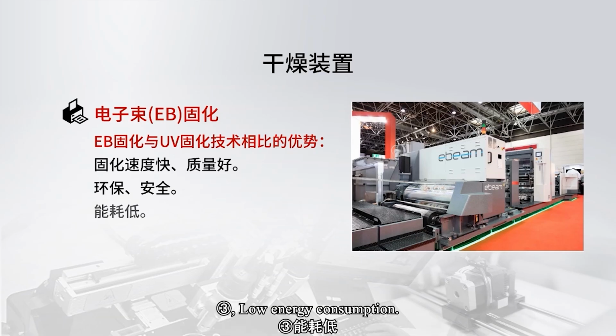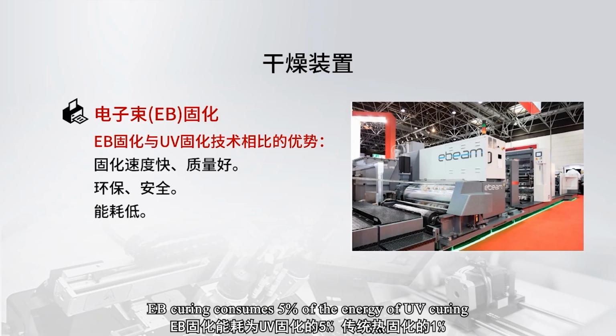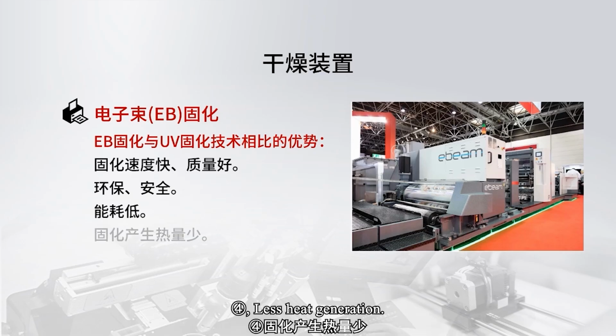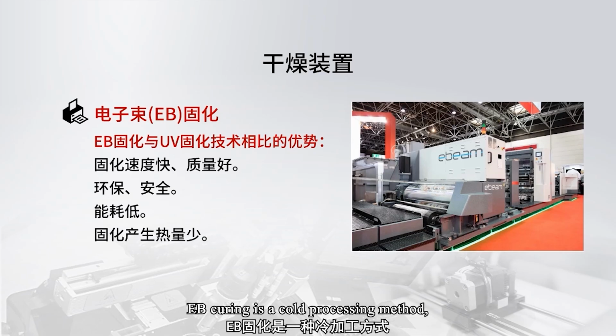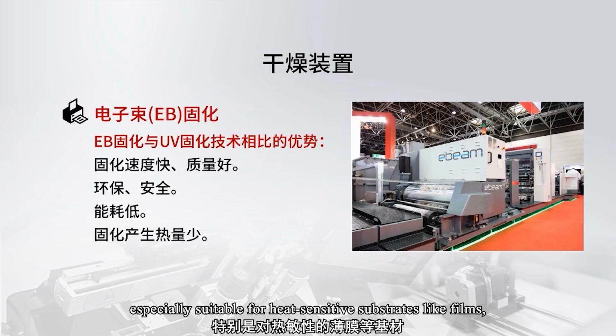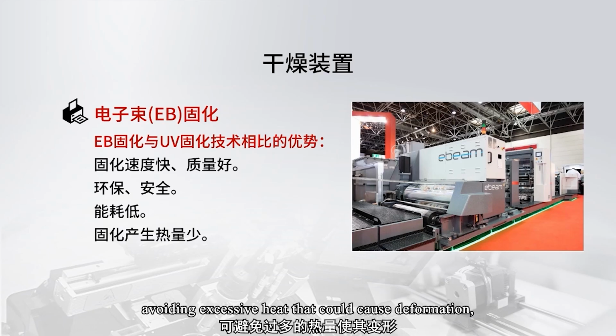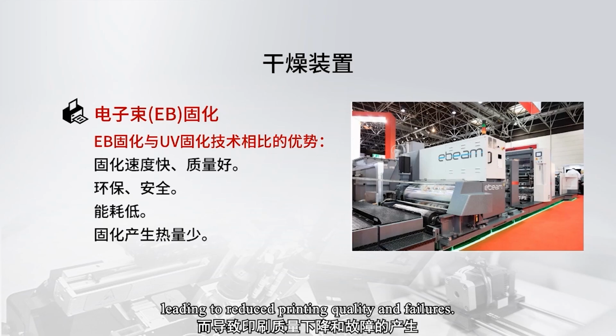3. Low energy consumption. EB curing consumes 5% of the energy of UV curing and 1% of traditional thermal curing. 4. Less heat generation. EB curing is a cold processing method, especially suitable for heat-sensitive substrates like films, avoiding excessive heat that could cause deformation, leading to reduced printing quality and failures.